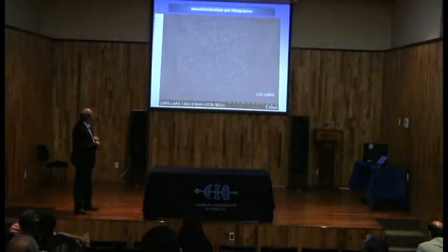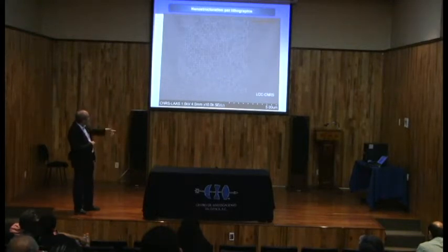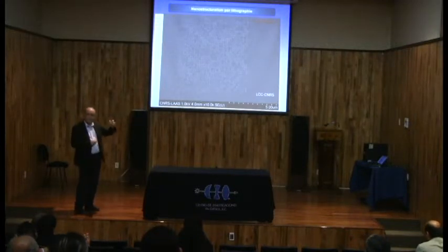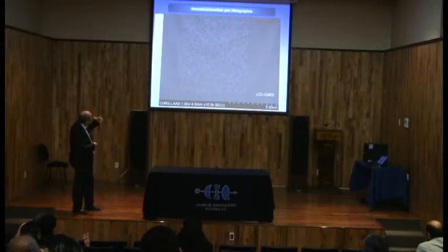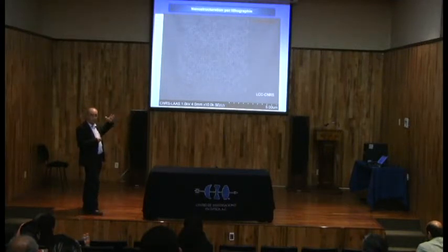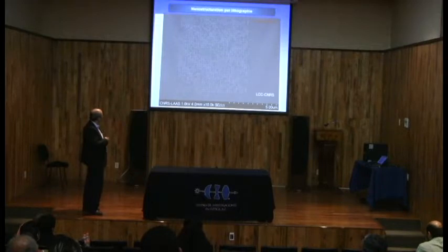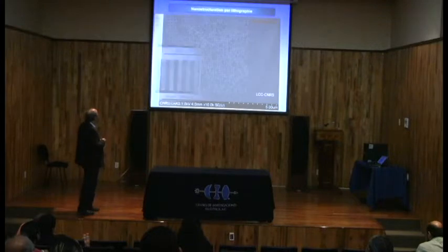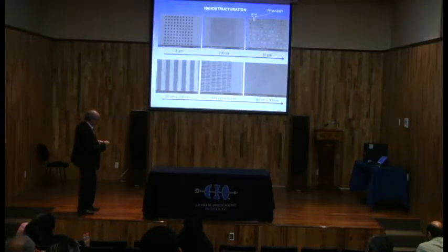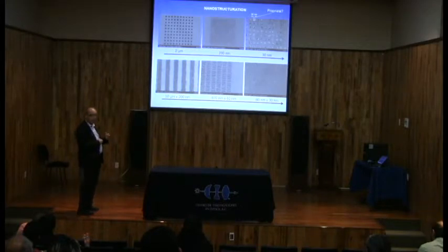So then we did this. What you can see, we can have thin films, spin crossover thin films with very well organized dots, and each dot has low spin, high spin conversion, and then it has its 2 states. Okay? So then this is a kind of hard disk molecular for molecular storage. It's already patented, and we are using it to make memories at very low dimensions. Okay? So then, of course, by E-beam lithography, we can play with the shape, the size of the dots. Even we can have lines here for optical applications.